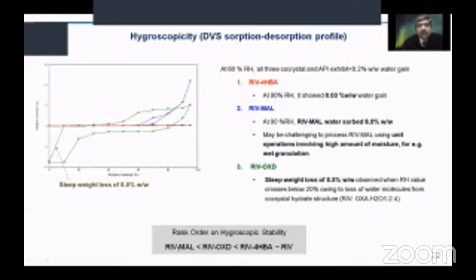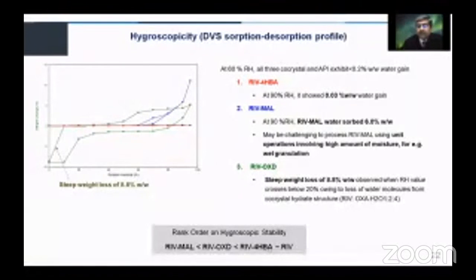On this axis, you have the relative humidity values, and this green color profile is for the co-crystal with the oxalic acid, which shows a steep weight loss of 8.8% at RH values below 20% owing to the loss of the water molecule from the co-crystal hydrate structure. The co-crystal that was obtained with oxalic acid in fact was a hydrate form, and when you store it below the 20% RH, it used to show a steep loss of 8.8%. So the rank ordering of the co-crystal candidates in terms of their hygroscopicity was that malonic acid co-crystal was the most hygroscopic one, followed by oxalic acid, 4-HBA, and rivaroxaban, which was almost equal to the 4-HBA.